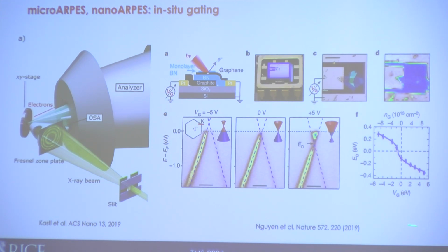So here's an example of the very first in situ gating plus ARPES measurements on monolayer graphene. The construct of photoemission ARPES means that we have to have an open top surface. We cannot work with dual gate yet. And the top surface, the sample that we measure, has to be grounded. The reason for that is because you have the beam coming in, you keep ejecting electrons, and remember, we have to keep this region field-free in order to preserve the information of the photoelectrons on their way to the analyzer. So the top has to be grounded. We can only do backgate. And also it has to be homogeneous and flat in the region covered by the beam. Otherwise, you will have broadening of your momentum resolution.